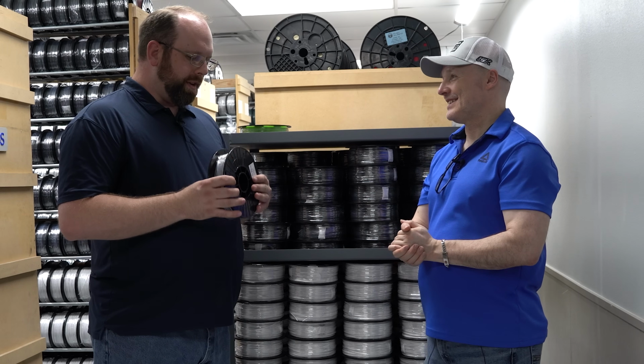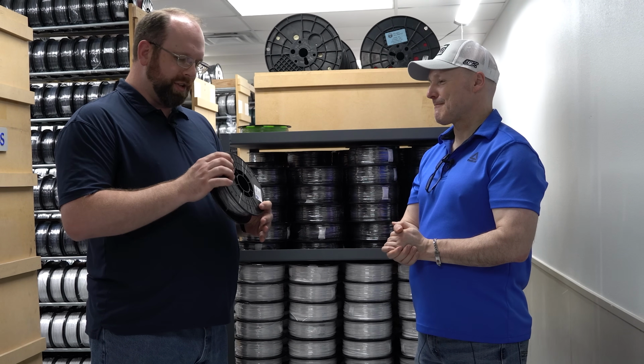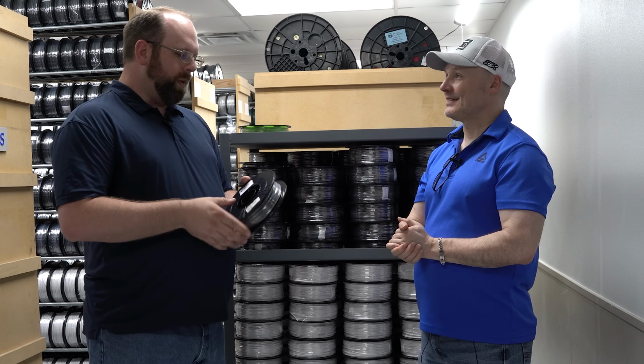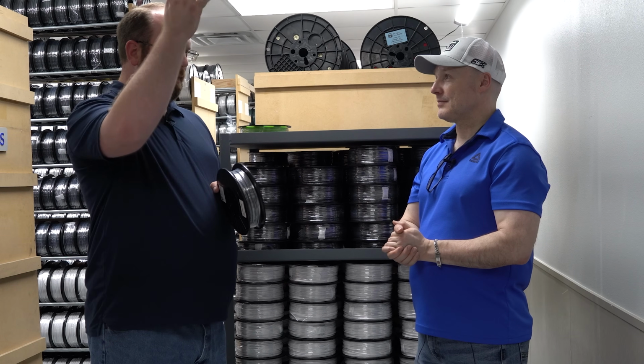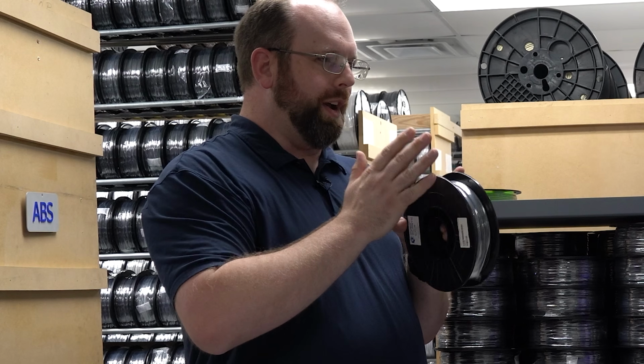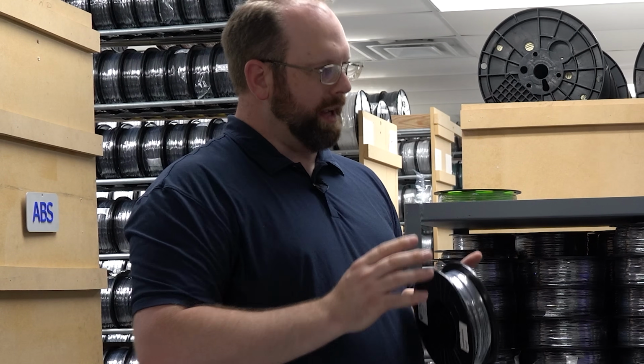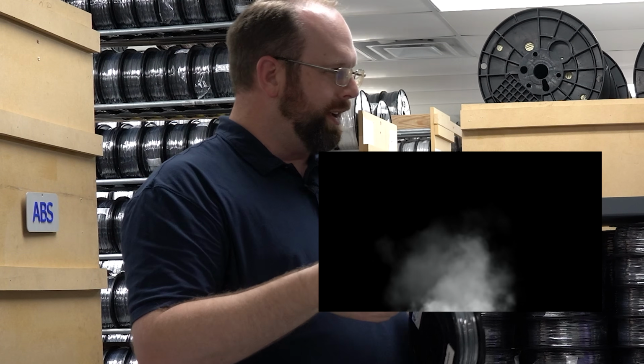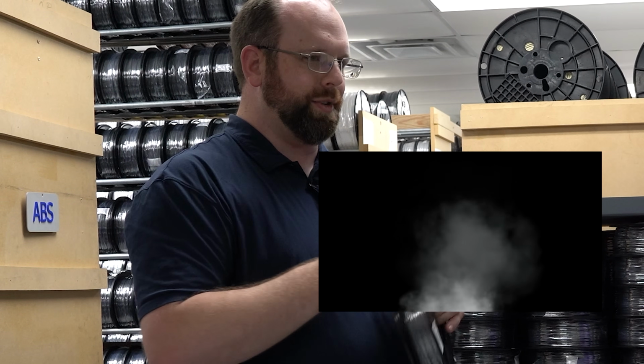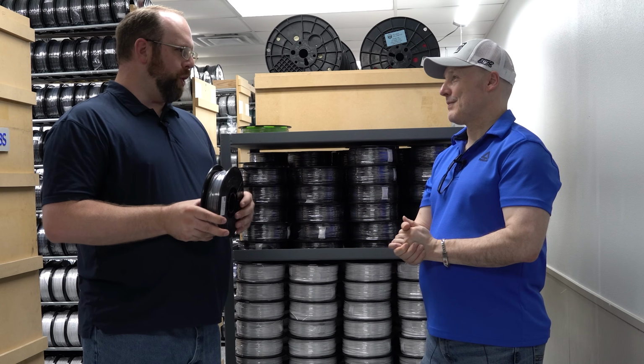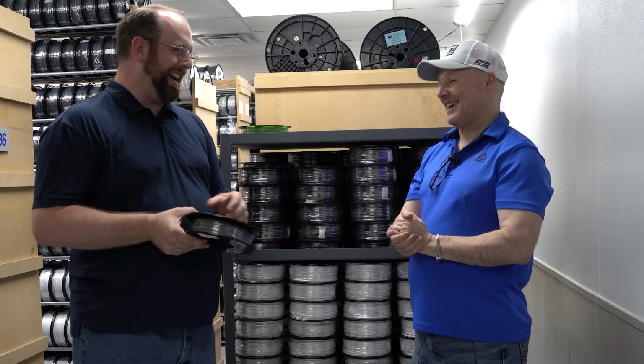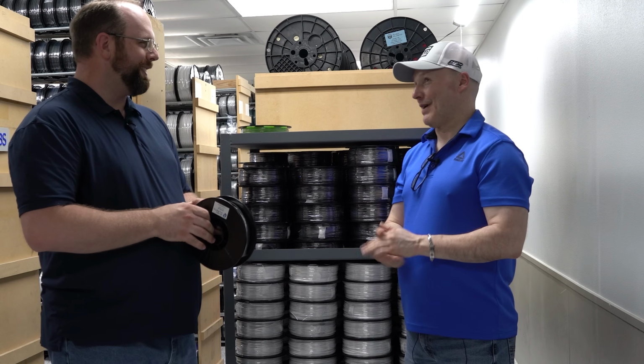Yeah, and there's enough moisture in here. I've heard numbers up to 30%. When this goes through your hot end, even with that laminar flow, that water's all inside it now. So that bacon popping is actually steam popping, more like popcorn. The water inside the filament gets excited by the heat from the hot end and turns to steam, which expands and creates little bubbles. And you end up with a nice foamy print that you don't want to be foamy. Exactly. It looked like a foam print, but I didn't want a foam print.